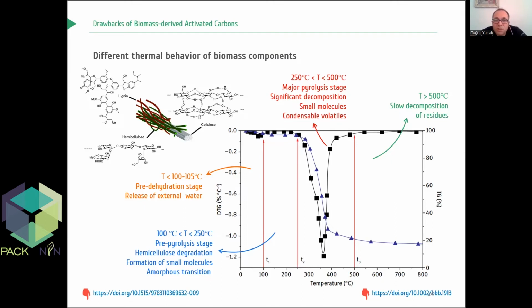During the heat treatment, on carbonization or activation, the amorphous part, mostly lignin, began to soften at the glass transition temperature. And this viscous structure inhibits the heat transfer and indirectly leads to negative effects on pore formation.